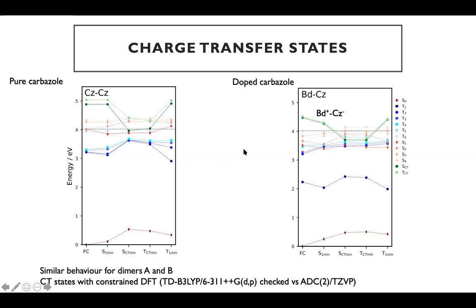Now, what happens when you consider the presence of the isomers in the system? Essentially, if you try to optimize charge transfer states in these dimers that I showed you before, you can get them. In fact, some of them stabilize a little bit, but they are quite high in energy. So what happens when you have this impurity in the system? When you have the impurity, the energy of the charge transfer state gets very low. So you expect that when you excite the system, this charge transfer state can be populated and can, in a way, facilitate the process after the initial excitation.